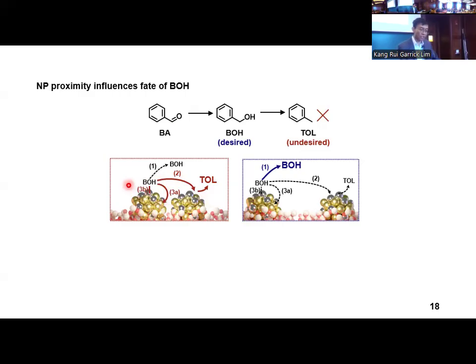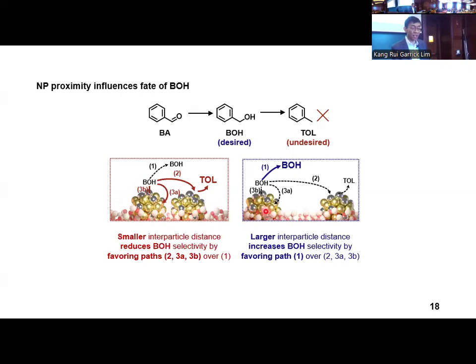Alternatively, benzyl alcohol can remain adsorbed on the same nanoparticle and form toluene. Since the lifetime of benzyl alcohol adsorbed on the nanoparticle depends on the benzyl alcohol surface coverage on the active sites of the nanoparticle, we propose that paths 1 and 3b likewise depend on the interparticle distance. Thus, we put forward that the interparticle distance affects toluene production and hence selectivity through 2 competing routes. A larger interparticle distance favors path 1, which results in freely diffusing benzyl alcohol in the bulk. On the other hand, a shorter interparticle distance favors path 2 and path 3, where benzyl alcohol is reabsorbed to form toluene.